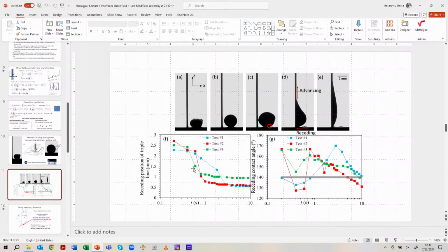You see, there is a very large error bar in experiments. There is a randomness in experiments which depends on surface roughness, on how quickly we heat the thing, how much oxide we have. So both things can happen. And in the end, we concluded that it really depends on how fast the flow starts and how well melted the material is.